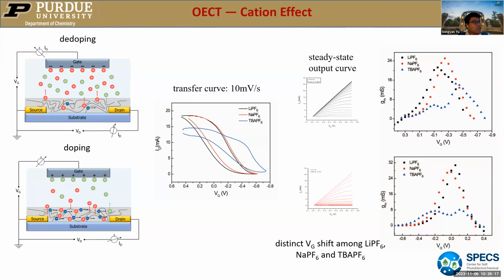So the last part I want to mention briefly is the OECT. Even in OECT for this polymer, we need to consider the de-doping and the doping process separately because they are not symmetrical. So here's an example of their transfer curve. We can see for TBAPF6, we need a higher gate voltage to de-dope the polymer. But for lithium, we just need a lower gate voltage.